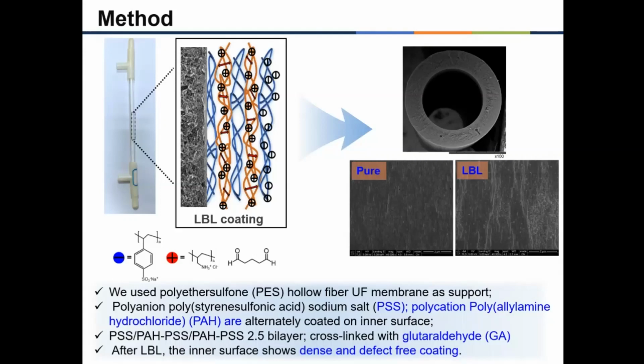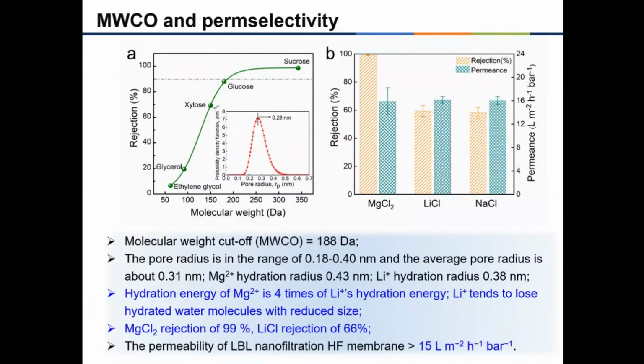After LBL, the inner surface shows a dense defect-free coating. We tested the molecular weight cutoff of this membrane and found MWCO about 188 Dalton. We suspect that the unique properties of the LBL separation layer may contribute to this best performance. Pore size acts as the most important factor for the separation mechanism of magnesium and lithium.